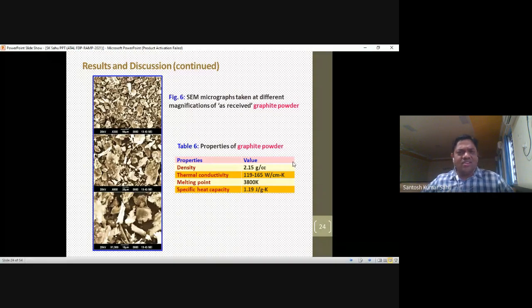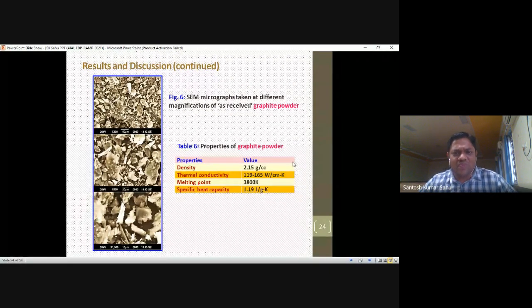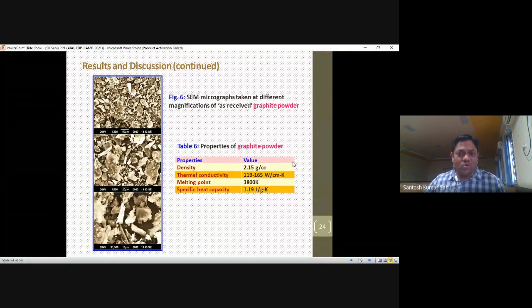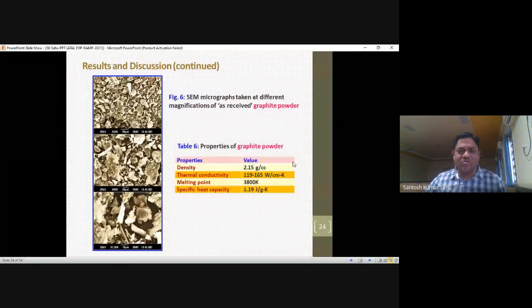Then we can see the different magnifications of the graphite powder, but you have to see table number 6. So why do you have to choose the graphite powder? Because here, just see the thermal conductivity: it is 119 to 165 watt per meter Kelvin. Its melting point is 3800 Kelvin. The workpiece we have taken is Inconel 718, and the Inconel 718 thermal conductivity is 11 to 14 watt per meter Kelvin.